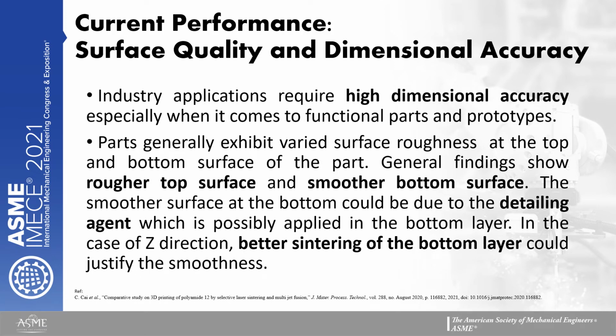As far as the surface quality and dimensional accuracy is concerned, industrial applications require high dimensional accuracy, especially when it comes to functional parts and prototypes. Parts generally exhibit varied surface roughness at the top and bottom surface of the part. General findings show rougher top surface and smoother bottom surface. The smoother surface at the bottom could be due to the detailing agent, which is possibly applied in the bottom layer. In the case of Z direction, better sintering of the bottom layer could justify the smoothness.